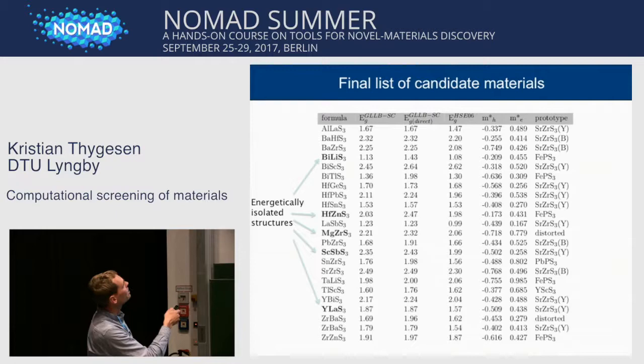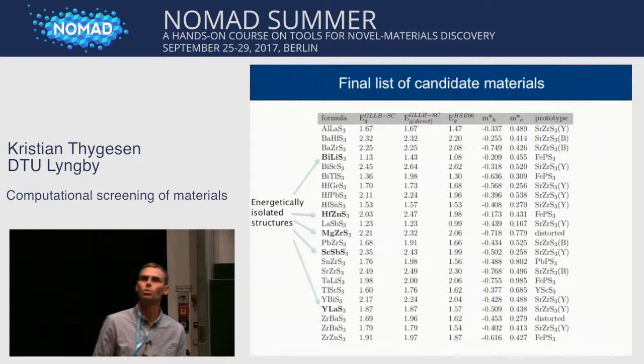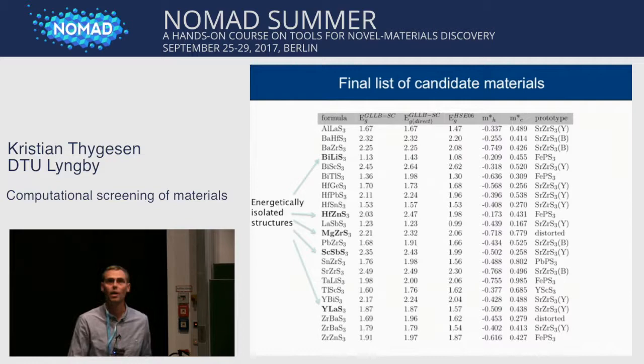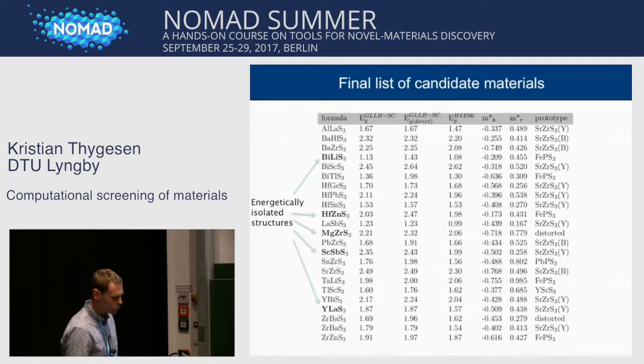In the other cases, there is at least one other structure that is within 25 meV per atom, as stable as this material here, and which might then have a different band gap. Okay? So we showed this list to some of our experimental colleagues. They looked at it and they said, yttrium lanthanum sulfide, that sounds interesting. We could probably make that. And they went to the lab and they managed to synthesize that material.